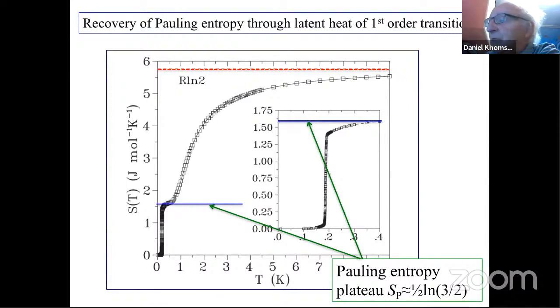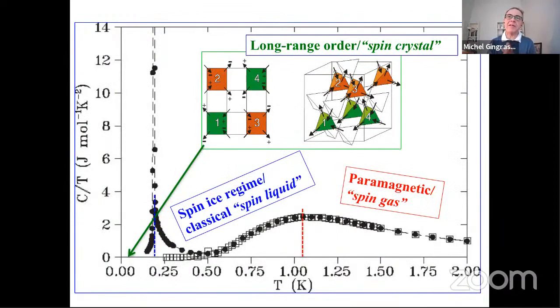What is this ground state? What is this ordering? What kind? You have magnetic field lines coming from these dipoles, and the system tries to eliminate the magnetic field energy as rapidly as it can over the unit cell, still fulfilling the ice rule. So this is what it looks like here. You have a set of tetrahedra which obey the two-in, two-out states on half the unit cell, and in the next half of the cubic unit cell, the spins are reversed. So it's a large unit cell antiferromagnet.